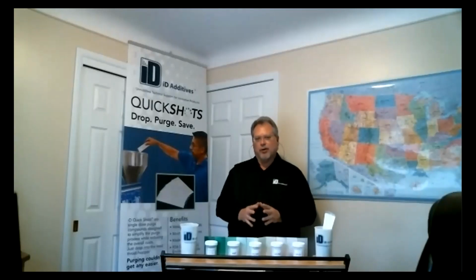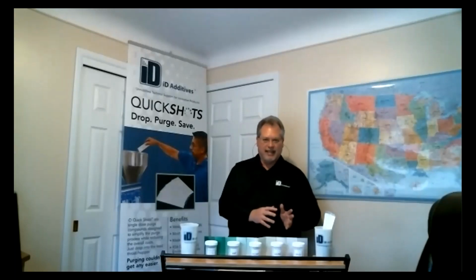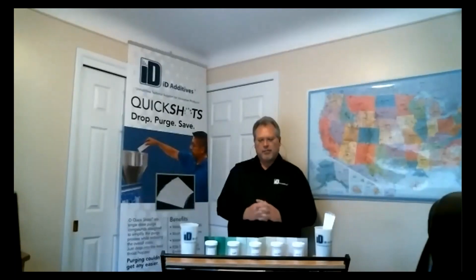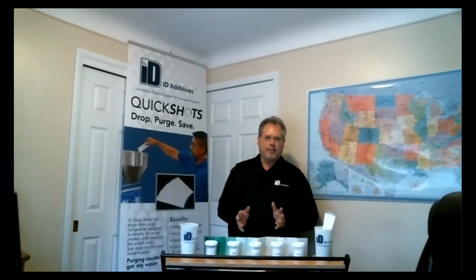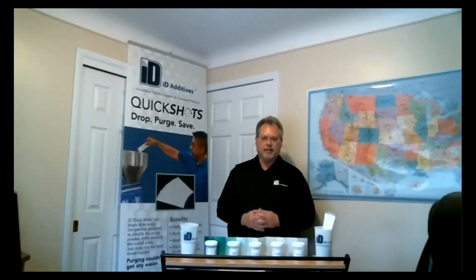But it's very important, I can't emphasize enough, to make sure that you purge out at the temperature of that material that you're cleaning out before you change the temperature settings. And sometimes people like to raise the back pressure when they go to purge. The only time that I really see that might be necessary, and where I've seen that it was a benefit, is when it was on a semi-barrier screw, and that otherwise the purge compound isn't in there long enough.